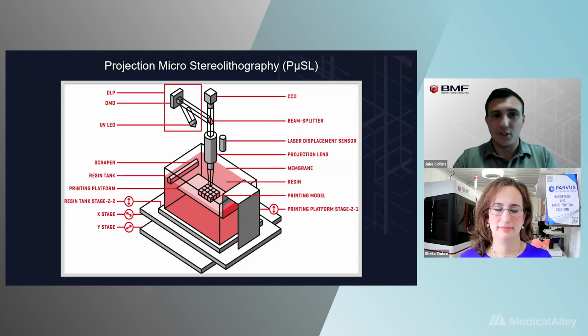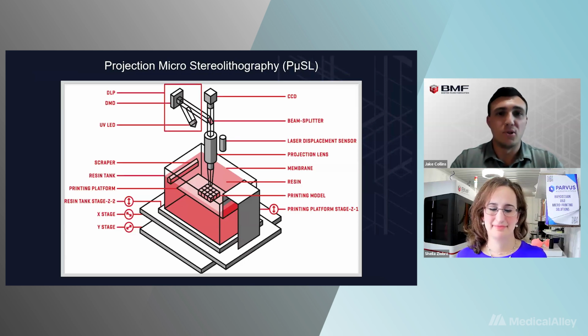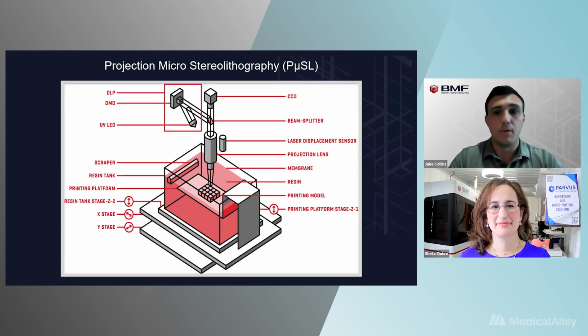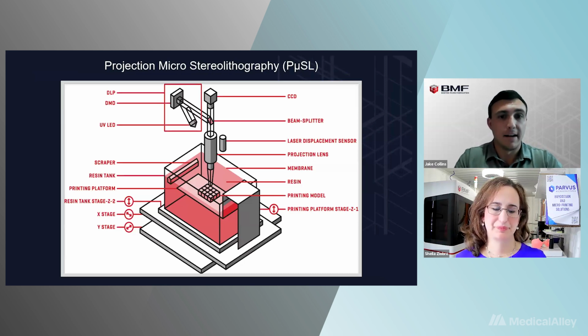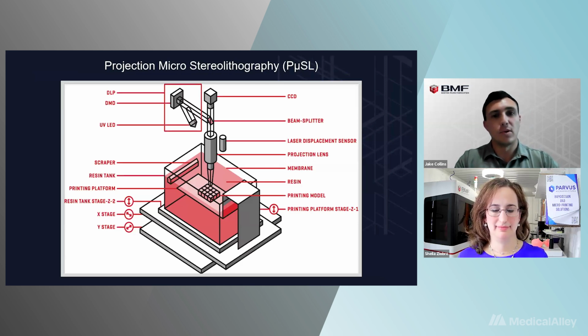So the way that we overcome this, you actually saw in the video, was we stitched together multiple zones of the build area. So the projection keeps that high resolution and perfect pixel pitch, but then in combination with a whole bunch of different stage movements, software processing allows the zones to be stitched together into larger individual parts or a high number of smaller parts to be printed at once. So with our S240, it's a 100 by 100 millimeter build area. So this allows you to keep that high resolution across the entire build platform, whether it's one single large part or hundreds of smaller parts. And you're not going to lose resolution in any spot on that build platform. So essentially, Pulse technology combines the best of both those two different methods to achieve those high resolution parts.